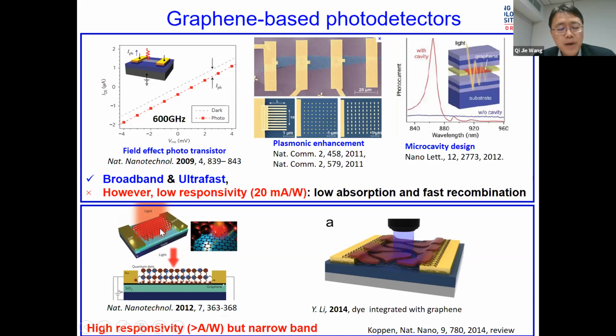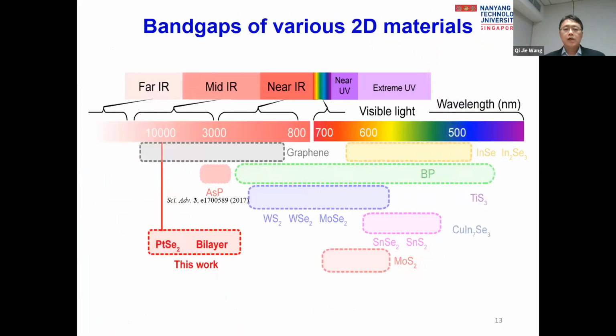Here the nanoparticles are used as a light absorber. Because the nanoparticles have a strong absorption coefficient, such a configuration can give really high responsivity. However, the current demonstrations using nanoparticles can only absorb light in the near infrared region. So we want to build a mid-infrared photodetector in 2D material.